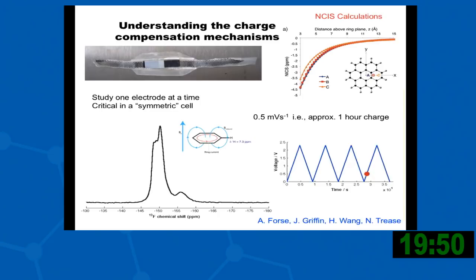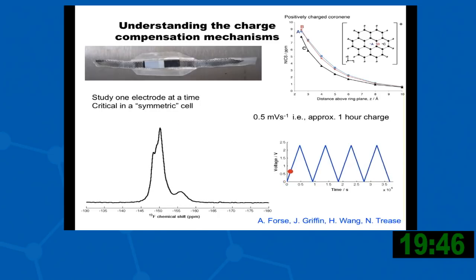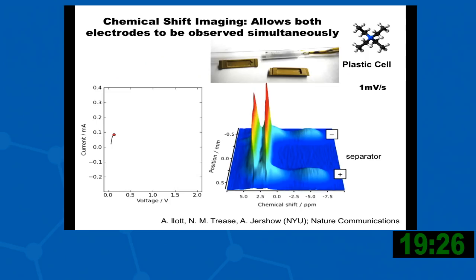And so the question is, I told you before it was aromatic. What's happening now? Well, what's actually happening is that you're pumping holes into the carbon, or you're pumping electrons into the carbon, and the carbons are becoming less aromatic. And so you shift to the right because you're aromatic, and you shift to the left, as these calculations show, because you're anti-aromatic. So we're actually probing the density of states in these carbon structures directly.